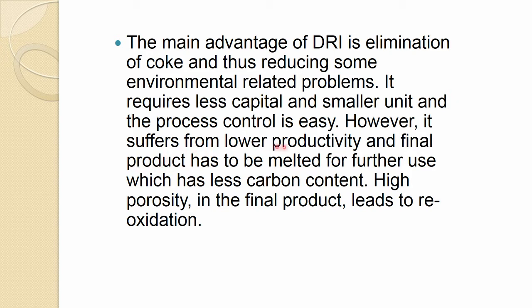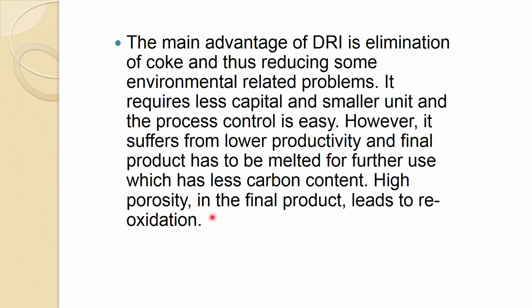In DRI — direct reduced iron — you have less carbon, so you need more energy to melt it later. There is also high porosity in the final product, which leads to reoxidation. Due to the sponge form, lots of porosity is present in the reduced solid iron, so when it comes out one has to be very careful it should not be exposed to air, otherwise it may reoxidize. Even during storage and transportation it may lead to reoxidation. These are some problems associated with DRI, but they can be easily handled.